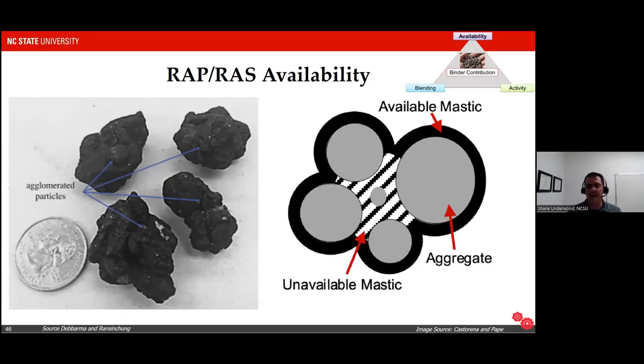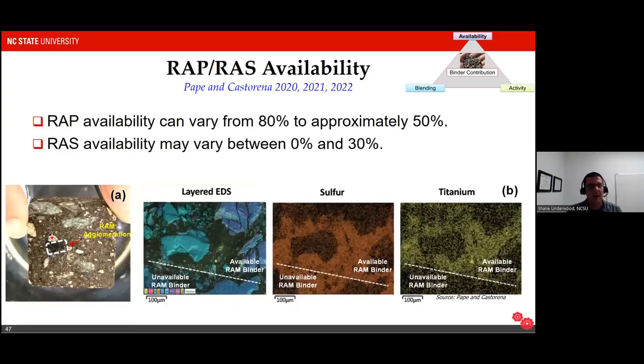Dr. Castorena and her student Sonia Pape have been championing a novel method where they actually use microscopy to look at how much of the binder is available. They can see, as you see in this picture, agglomerations of recycled material that are not becoming undone when it mixes, and they can actually see that through the microscope using X-ray techniques to measure the quantity of material in those samples.